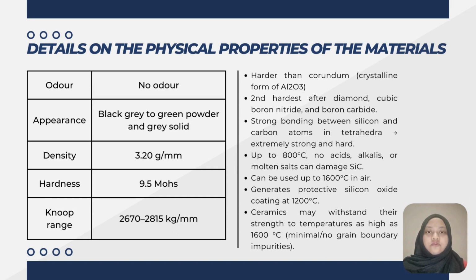The ceramic is a high-quality refractory material due to its strong thermal conductivity, excellent thermal shock resistance, minimal thermal expansion parameters, as well as high resistance towards corrosion and oxidation. The strong bonding between the silicon and carbon atoms in tetrahedra that make up silicon carbide's crystal structure results in a material that is extremely strong and hard. Up to 800 degrees Celsius, no acids, alkalis, or molten salts can damage this material. Silicon carbide can be used up to 1600 degrees Celsius in air and generates a protective silicon oxide coating at 1200 degrees Celsius. Ceramics made of silicon carbide with minimal to no grain boundary impurities may retain their strength to temperatures as high as 1600 degrees Celsius.